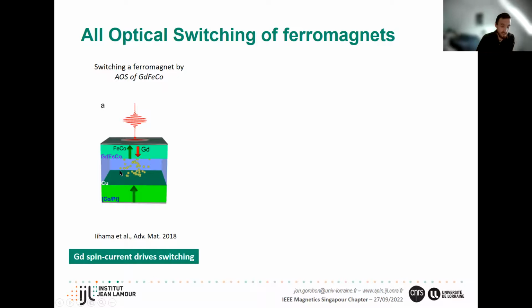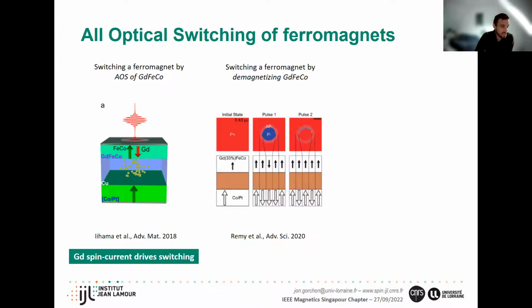to us. A few years later, we discovered that in this similar type of structures, if we increase the content of gadolinium in such a way that eventually the gadolinium iron cobalt does not switch by itself. So in order to have this all optical switching, you need a certain composition. If you put so much gadolinium that it doesn't work anymore, so you only get demagnetization of the top layer, you can still switch the cobalt platinum. You can see this here.